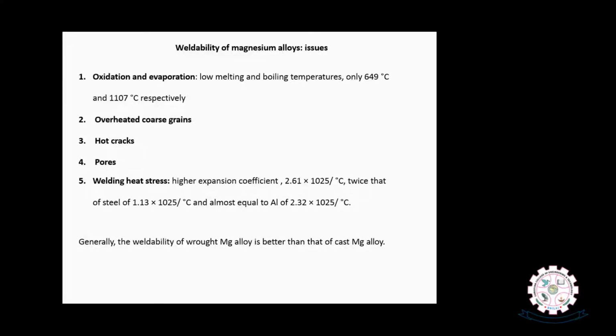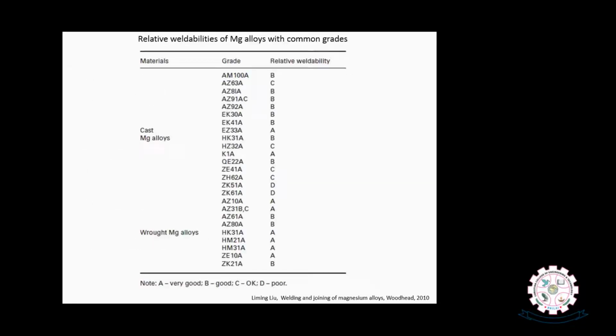Once the welding process is over, development of cracks is another big problem in magnesium alloys, and presence of pores, and also welding heat stresses are the usual challenges associated with the welding of magnesium. So generally the weldability of wrought magnesium alloys is better than cast magnesium alloys. So these are typical weldable magnesium alloys, and the corresponding grades you can compare here. Most of the magnesium alloys except the ZK series are good, or at least in the very good category.